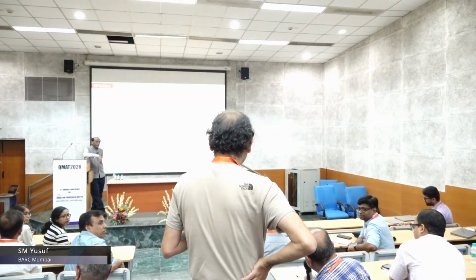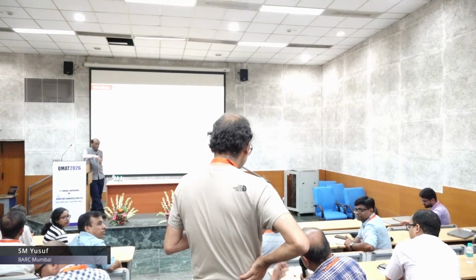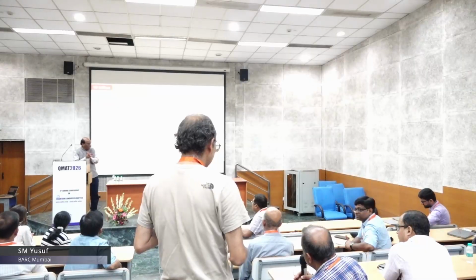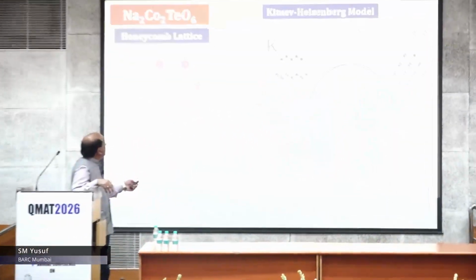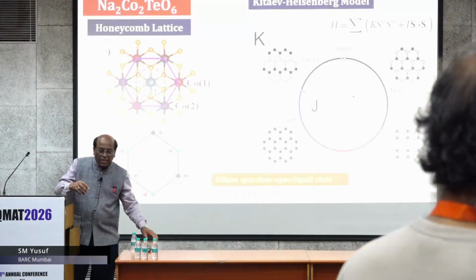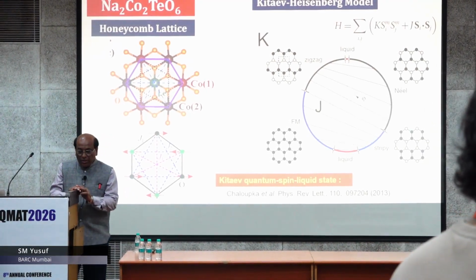There is a very nice talk, and this is regarding this cobaltate. Usually in d5 systems, the Heisenberg term dominates the Kitaev term, and it's very difficult to find the spin liquid state. But on the contrary, for this d7 system you do see a spin liquid in the phase diagram. Any understanding of how the Heisenberg term is weakened? You are talking about sodium cobalt tellurium oxide? Yes.